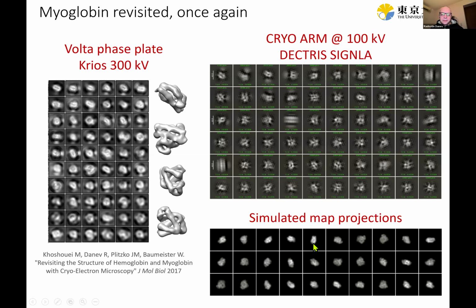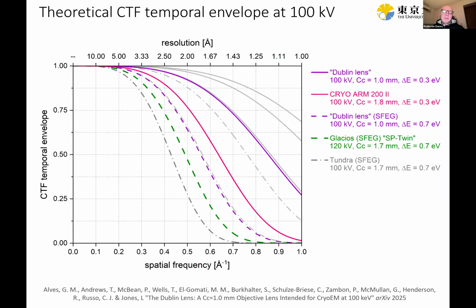So these kind of classes where we see more contrast features will be more viable to achieve in practice, of course. And orientations of the molecule where you have less features and less contrast, of course, these kind of classes will be more difficult to get. And also these kind of orientations in the 3D reconstruction will be more challenging to assign. Therefore, I think we are kind of on the verge, you can say. So we get some classes that show features that are similar to the projected ones, but still no outcome in 3D.